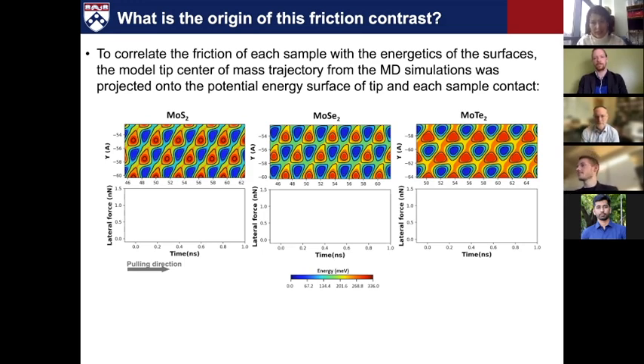Point about exactly the same slide you have, where we see the MoS2, MoX2 comparison. I saw exactly the same trend in the electrocatalytic activity for hydrogen evolution when I was working with Jonathan Coleman. In that project we had a lot of 2D materials. I compared MoX2 with WX2, with sulfur, selenium, and telluride compounds. And so the friction force, you say, is larger for MoS2 and then gets smaller toward MoTe2. Exactly the opposite direction goes for electrocatalytic activity. MoTe2 is the most active, and then MoSe2 and MoS2.